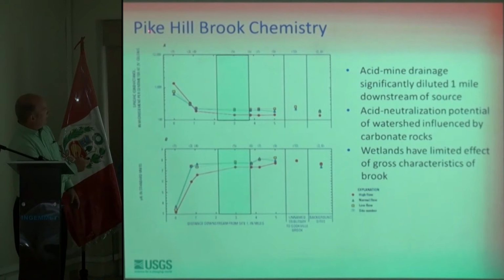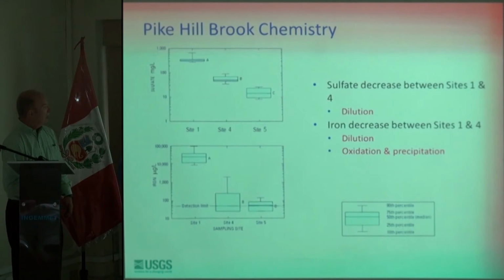So for example, on this diagram, you can see distance downstream and specific conductance or total dissolved solids or pH on this diagram. The reach that includes the wetlands is shown by these boxes here and here, so that you can see as the contaminated stream enters the bigger stream, you get rapid dilution and you get rapid neutralization of pH. And you also notice that in the wetlands, at least as far as these major water quality parameters of pH and specific conductance or total dissolved solids, the wetlands do not seem to be having a big effect.